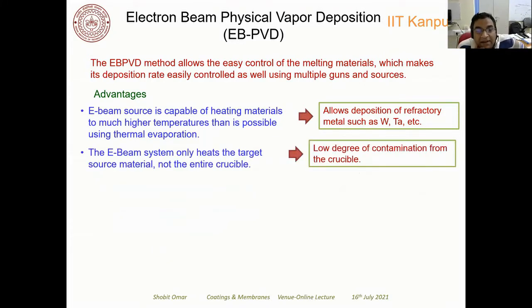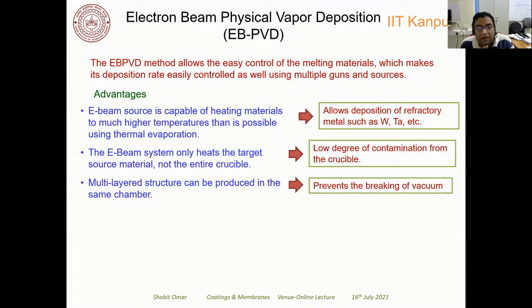The other thing is that since you are locally heating the target, you can use different types of target inside the same vacuum chamber. So you do not basically break the vacuum. You don't have to break the vacuum to change the target every time, so you can make multi-layer structures in the same chamber. And of course the contamination is not much because you are not heating the crucible, you are heating just the material, locally. So there is a low degree of contamination from the crucible in the thin film that is deposited on the substrate. So these are the main advantages of using the electron beam PVD technique.